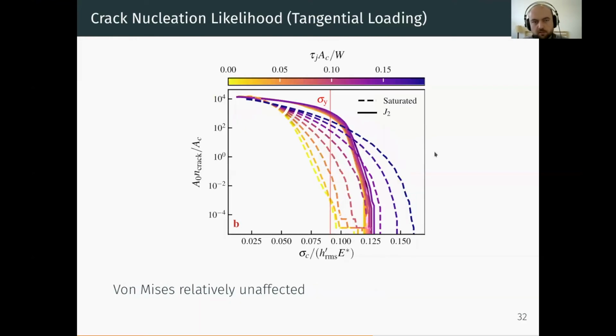I also did simulations where I do a normal loading, and I apply a shear stress to simulate the onset of sliding. And what I see in this case is that in the saturated case, where again, deformation is basically elastic, as I increase the load, I have an increase in my crack nucleation likelihood because the tensile stresses in the system increase. But in the case of having a full description of plasticity, I don't have this increase of the crack nucleation likelihood. So the probability is basically unaffected by the application of a shear stress in this case.